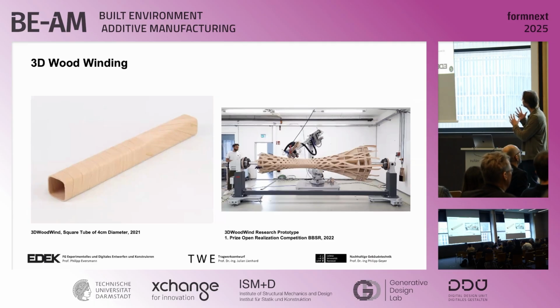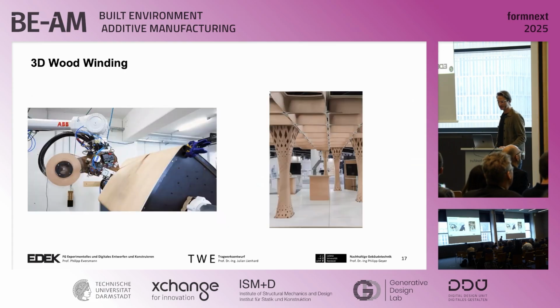So starting from really small dimensions in the first projects, a tube of 4 centimeters, we scaled this up really quickly, for also a project we had to realize, up to a one-to-one building system and ceiling structure. You can see that here. And unlike these other fibers, it's a really, really thin material, 0.5 millimeter, quite fragile during the application.